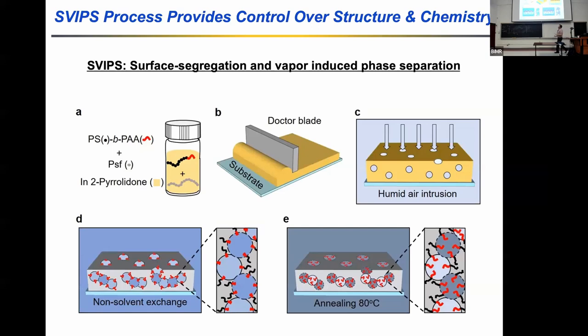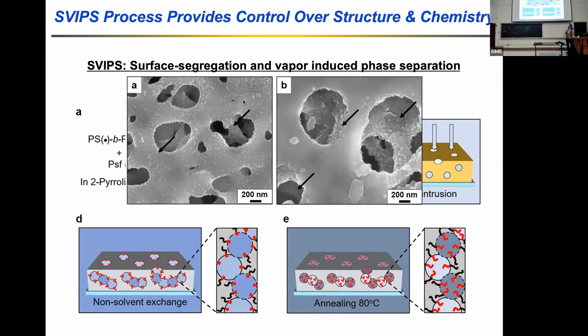The other nice thing, then, is that the block polymer is amphiphilic. The polystyrene bits, like the polysulfone, sort of bury themselves in the matrix of the membrane, whereas the polyacrylic acid bits are hydrophilic and like to stick out into the non-solvent, the aqueous environment. And if we anneal them, we'll really be able to pull them to the surface. If you look closely, those little light lumps on the surface at these high magnification SEMs are consistent with the brush size of these polyacrylic acid moieties. So we're happy with this nice spongy structure, and we've got the polyacrylic acid brushes pulled to the surface.